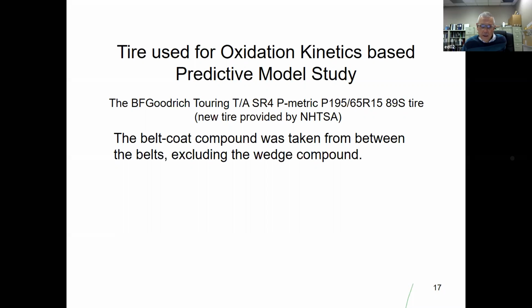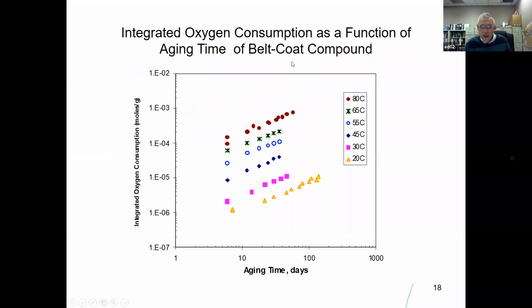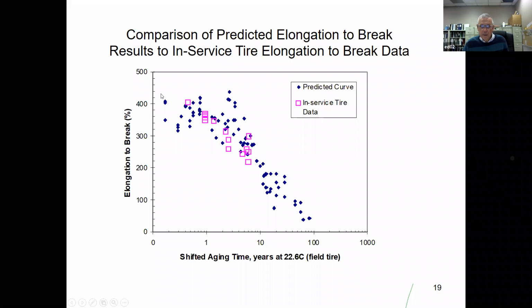And so we're left with oxidation. The next 3 slides are from last week's presentation, where we did a service life prediction model based on oxidation kinetics. We measured integrated oxygen consumption as a function of aging time at a series of temperatures, and using that data, we were able to develop a prediction curve, which was in very good agreement. So with all this data, we're saying that the oxidation is able to explain all of the changes in the crosslink density and the other properties that we see.